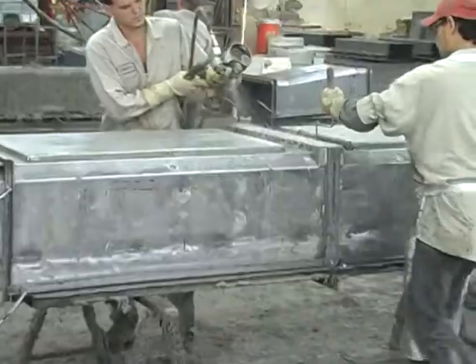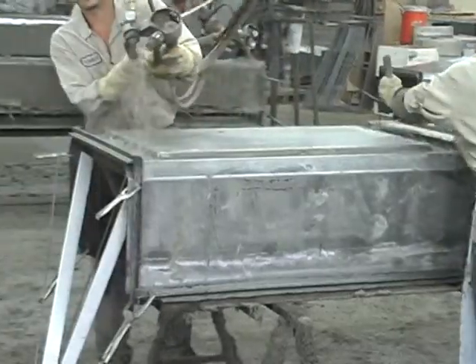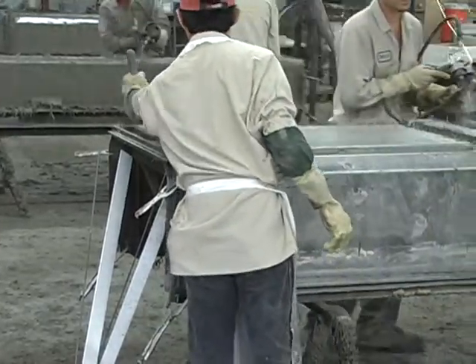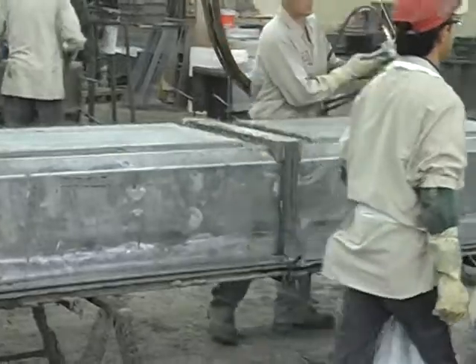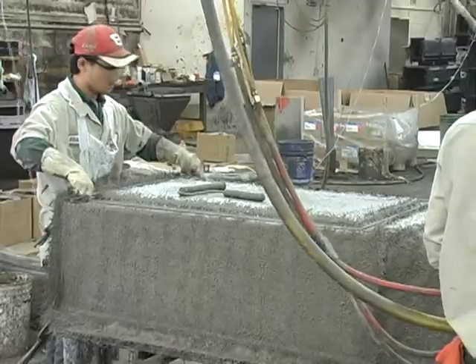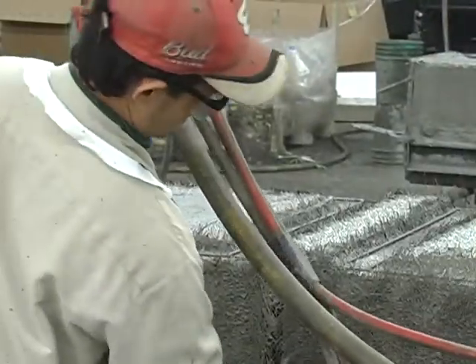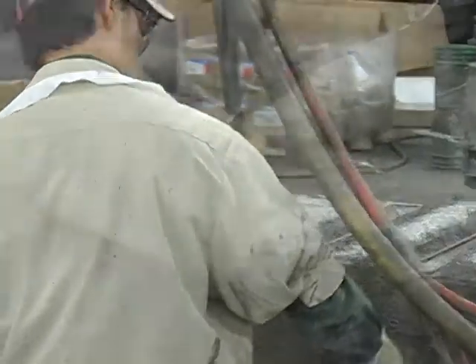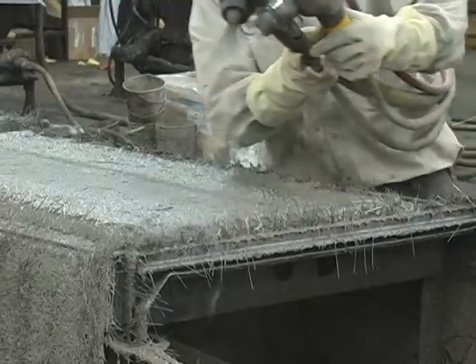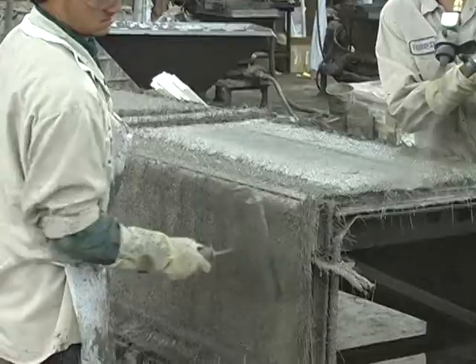Manufacturing pedestrian-rated channels is done with steel molds and a spray-up process. The inside of the channel is the mold side, which produces a smooth finish. Reinforcing rods and structural formers are used to add strength at the corners and edges. A slurry of polymer-enhanced concrete is sprayed, and chopped alkali-resistant glass fibers are added to the mixture. Several layers are sprayed to build to the required design thickness.